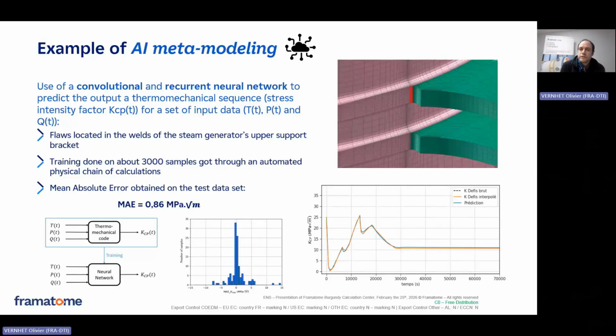So here you got the study that we did. We postulated defects in the weld between steam generator upper support brackets. So you can see the flaw in red that we considered, right in the middle of the weld between the bracket and the pressure boundary of the steam generator. So we postulated defects there. We went through the whole physical chain of calculation using Systus and the fast fracture post-processor. So this helped us evaluate stress intensity factors. We ran this calculation for around 3,000 samples.